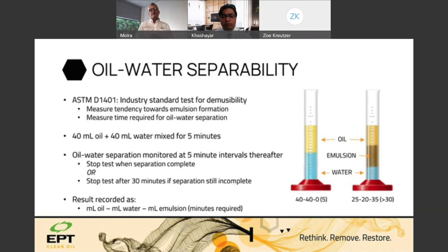Emulsions would be very difficult to manage normally, okay? The worst case scenario would be to get an emulsion through our bearings. We can separate the free water out and make sure that our oil inlet to the bearings is not taking in free water, but an emulsion could get sucked into the bearing. So we test water separation to make sure that we don't have emulsions. When we do have emulsions, we need to take corrective actions relatively quickly because emulsions would be very harmful to our system.